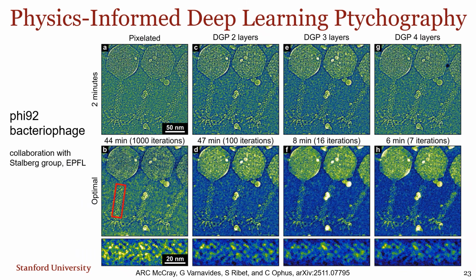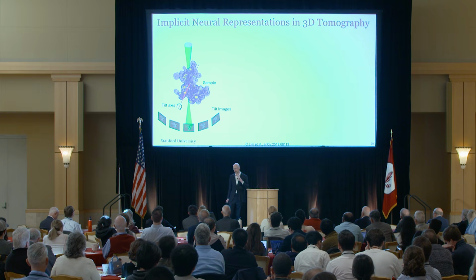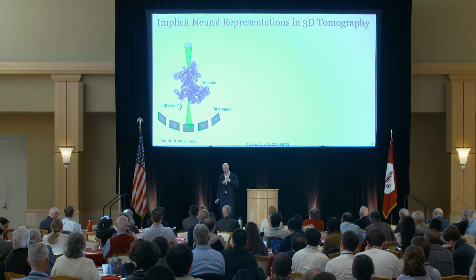But I just want to show that the pixelated reconstruction, right, you can immediately see the image quality of the deep generative prior versus the pixelated one. And it's quite robust. As long as you use one of these physics-informed machine learning models, you're able to get a much more efficient and often much faster reconstruction of your sample. Okay, so let me show you one last experimental example, again returning to 3 dimensions here.